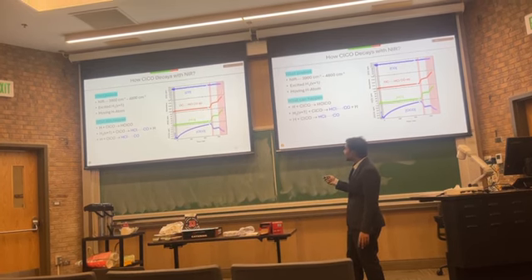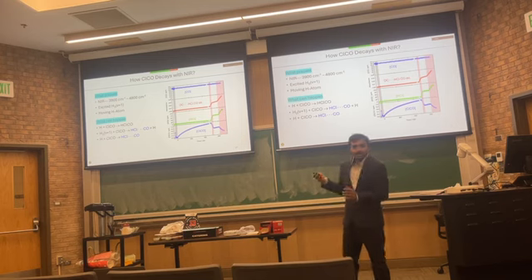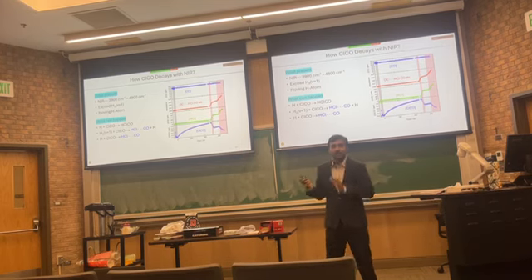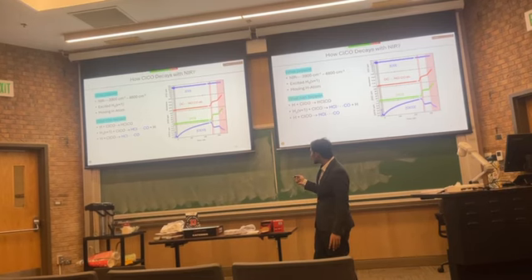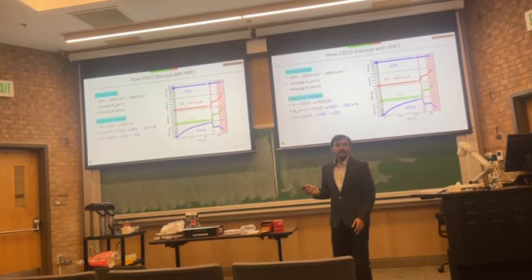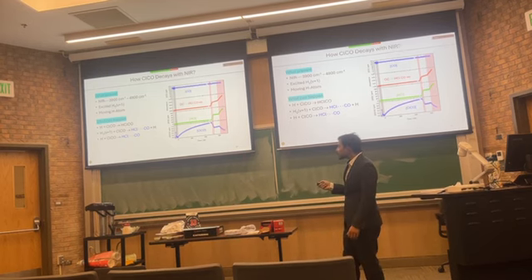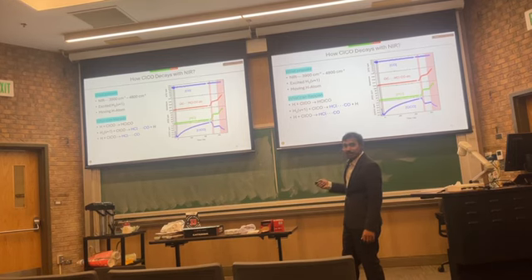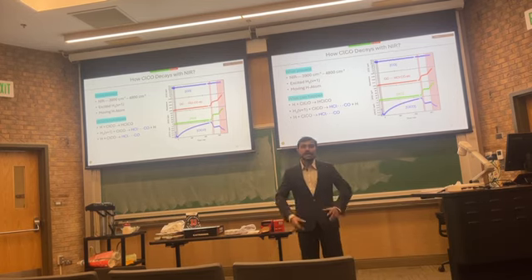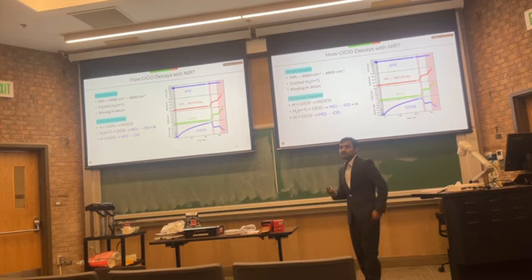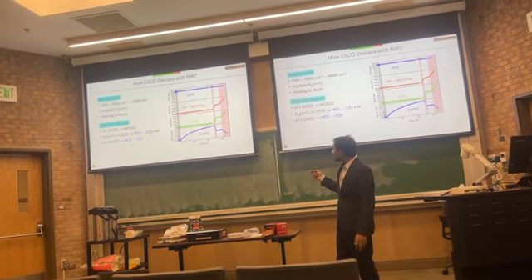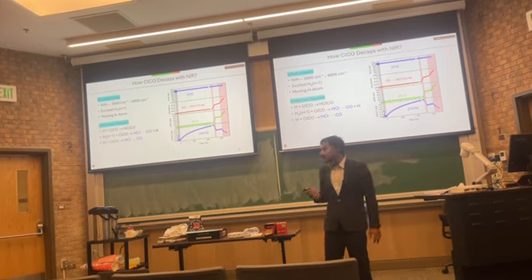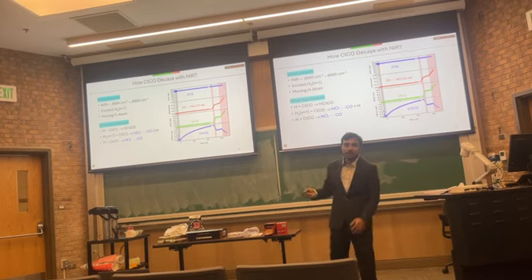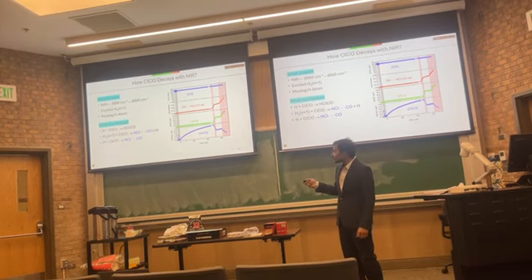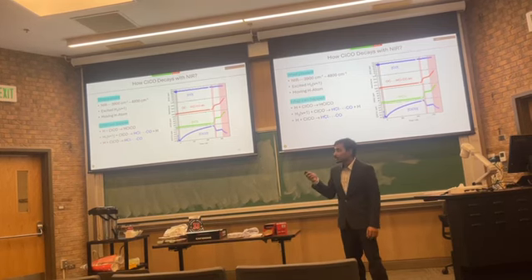But when we expose it to near infrared again, we see HClCO grows again. This growth is faster than before, because here you see the slope is slower and this slope is bigger. So it was faster. Now the problem is, is it faster because both are happening, or because we are producing hydrogen atoms again, so we have more hydrogen? We don't know, and we don't have an experimental way to isolate that. So both of them actually can happen, but for sure the last one, a hydrogen atom reacting with ClCO, is definitely happening. So we could not exclude the middle one, but we could confirm the bottom one and exclude the first one.